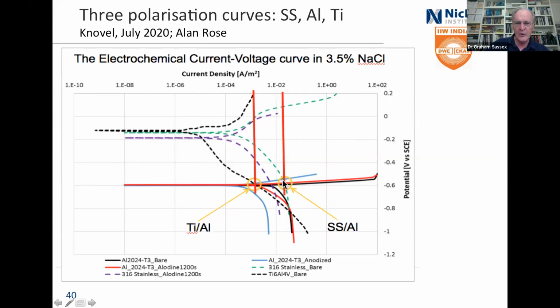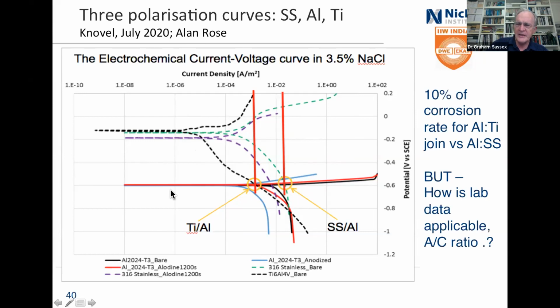And compare that with looking at stainless steel, this is the blue one, with the aluminium, or the aluminium with treatment. And you get about 10% of the corrosion rate with the aluminium titanium compared to aluminium stainless steel. So that means you can actually look at it and say, well, okay, this treatment is going to be 10% better, or hopefully even better there. And look, current densities, amps per meter squared, going down to really tiny, but up to enormous. This is basically electrochemistry, and that's all it is. It works every time because it's basically measuring what is happening there.